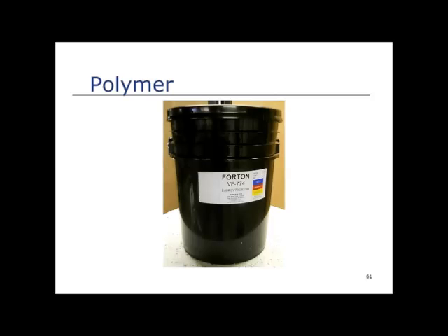What is the temperature range for casting and curing? Don't let it freeze and don't cook it. 50 degrees Fahrenheit to, let's say, 90 degrees Fahrenheit, or if I had to put a number on it, 10C to 34C. I'm guessing that's a conversion. I've cast in 100-degree temperatures without any issues.